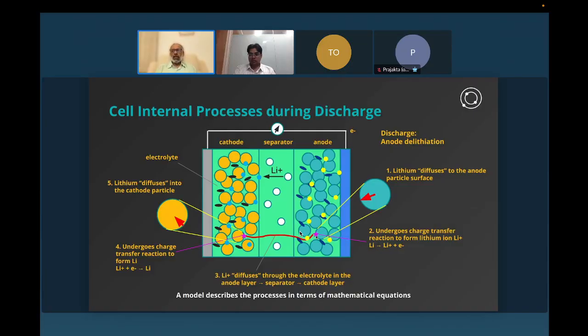And the third is the Li+ that's now generated at the surface first diffuses through the electrolyte contained on the anode side. So look at it as swimming through the electrolyte. That's a diffusion. And then it enters the separator. And similar to what happens in the anode, it now diffuses through the separator. It sees a different porosity, it sees a different resistance as it goes through the separator. And then it enters the cathode side.